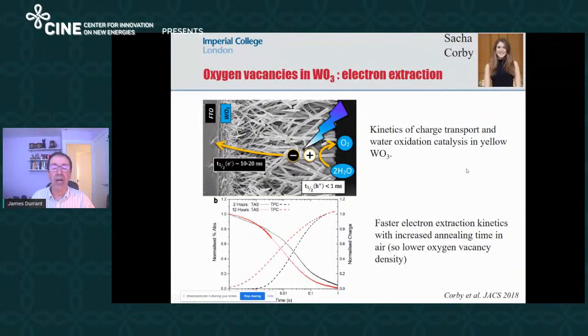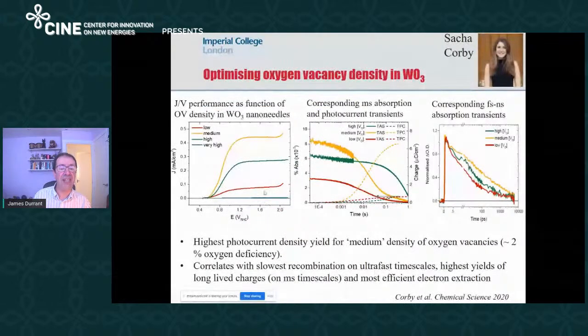As another example, tungsten oxide is particularly prone to oxygen vacancies. And this is just a study showing, for example, that if you vary the annealing time in air, and so in this case we are removing oxygen vacancies by annealing in an oxygen environment, then what you can see is that as you decrease the oxygen vacancy content, the kinetics of getting the electrons out of the system gets faster. And indeed, what we've observed in a rather more detailed study is that if you vary the oxygen density in tungsten oxide, then there's actually, at least in terms of these nanoneedle tungsten oxide photoanodes, an optimum oxygen vacancy density, which is neither too high nor too low.